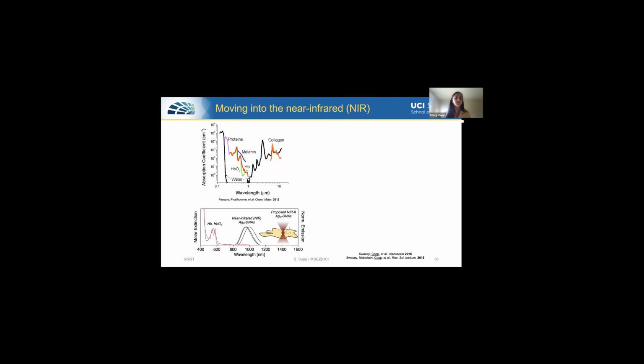But the problem is we don't have too many things, molecules, nanoparticles, et cetera, which emit a lot of near infrared light. So we are looking for near infrared silver clusters, even out here where we haven't discovered any. The reddest ones we've discovered so far are here, well within the near infrared. And this is within this window where not very many of our biological tissues are absorbing, scattering, or emitting light.